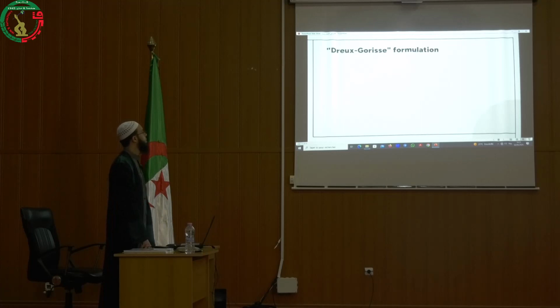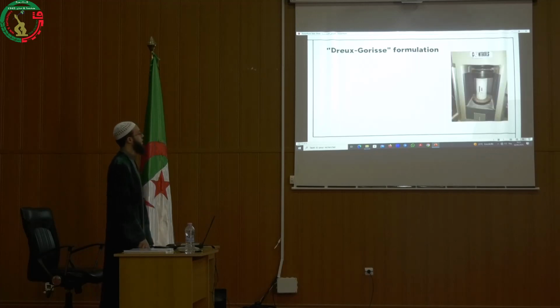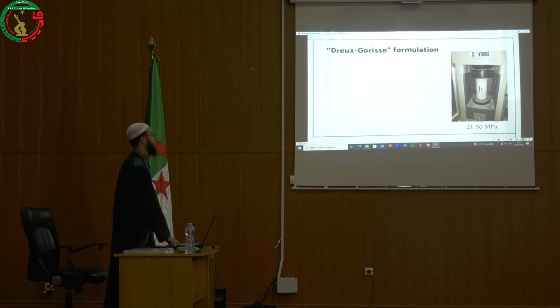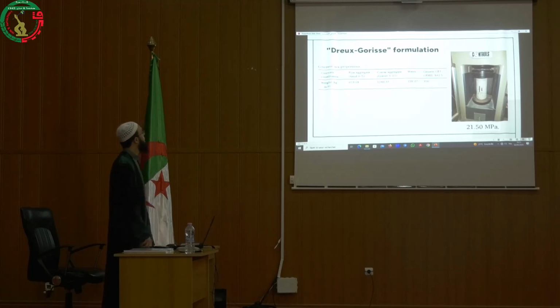To determine the concrete mix proportions, we employed the Dreux-Gorisse formulation method. This method is a reliable technique widely used in concrete composition determination. After casting cylindrical specimens, we conducted a compression test, which revealed an average compressive strength of 21.5 megapascals at 28 days. The following table shows the proportions of the materials required to achieve this compressive strength.